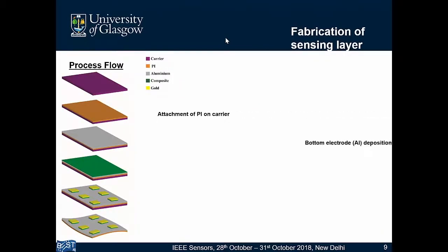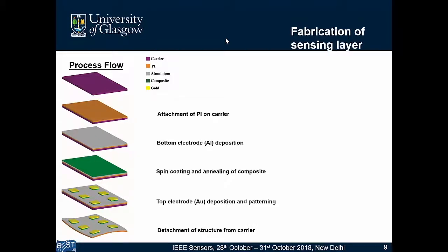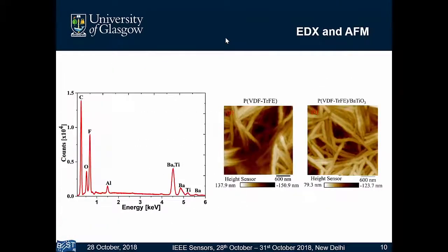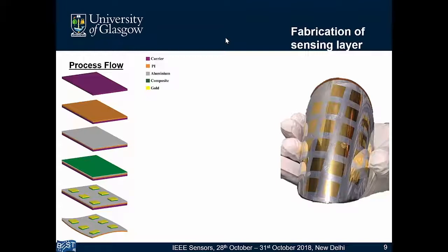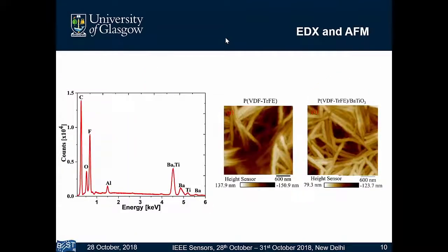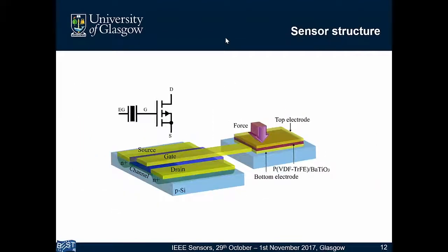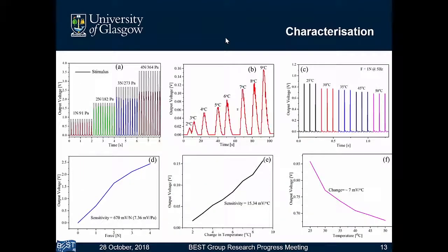We made a simple capacitive structure on a polyimide. It has an aluminium bottom electrode, a composite as the dielectric, and a gold top electrode. By EDX and AFM, it has been observed that by addition of nanoparticles, we are not only suppressing the pyroelectric but also enhancing the piezoelectric property. We connected the extended gate here. The response gives 670 millivolt per Newton sensitivity to force, and sensitivity to temperature when both were applied together was just 7 millivolt per degree centigrade, which shows a significant decrease in sensitivity toward temperature.